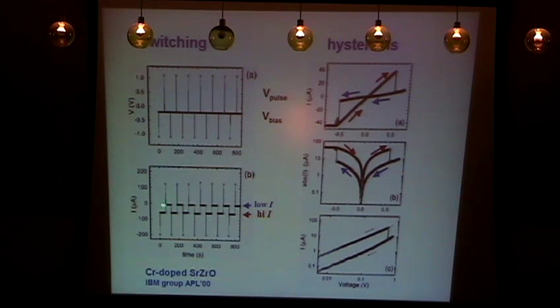But the interesting thing is that after each one of the pulses, you can leave the system in a metastable state, which remains for a long time. That is the non-volatile memory, which can have a low current or a high current. So this corresponds to two different resistance states, which are stable. The counterpart is hysteresis experiments, in which you run the voltage up and down, or the current up and down, and what you see is that the system switches from a low resistance state to a high resistance state once you go through certain thresholds in voltage or in current.